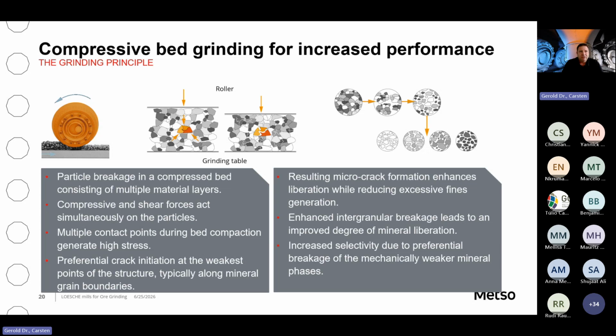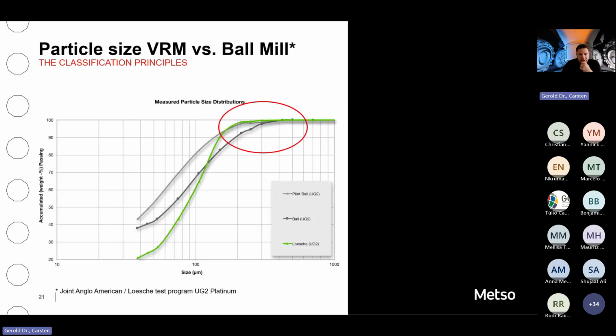To add that, I forgot to mention that, because usually you don't have that much control over your grinding forces. Within the VRM, you have the hydropneumatic spring system where you can steplessly control your grinding forces and thereby really optimize them for the purpose. And the result of this, the way we grind, within the movie, you saw that after being ground, the material is accelerated and then gets the chance to be classified. So with this very quick internal grinding classifying circuit, after 1 or 2 grinding contacts, we classify the material. So we take it out as soon as it's fine enough and according to the specification. And that results in a completely different product particle size.